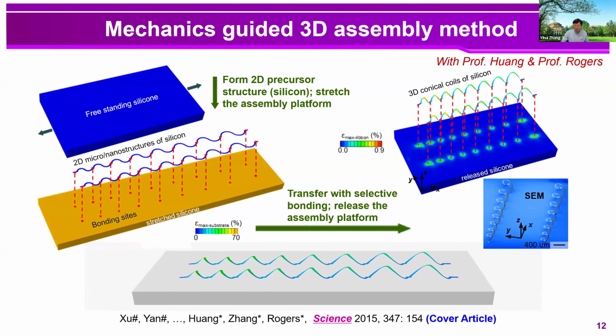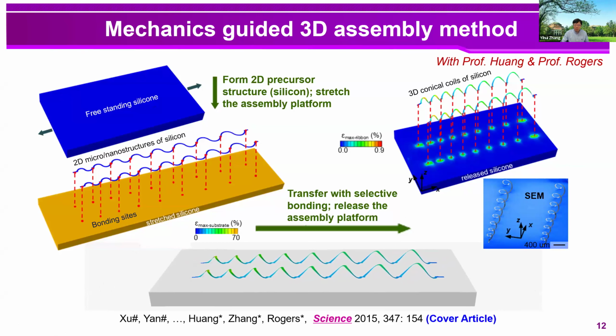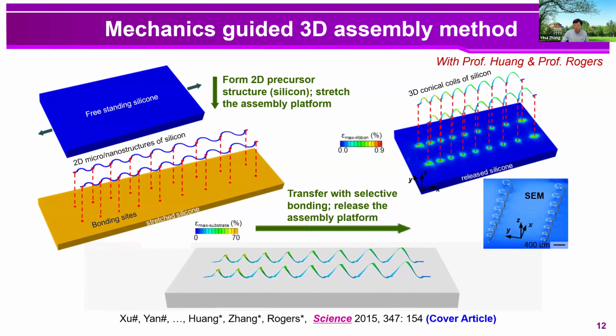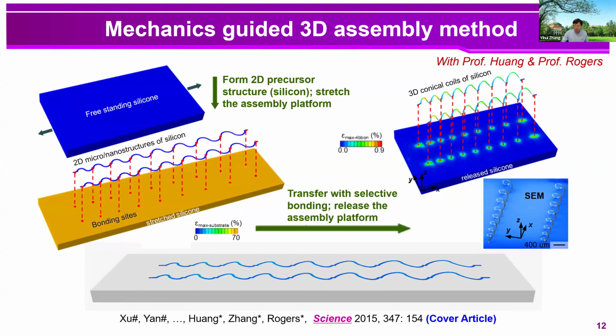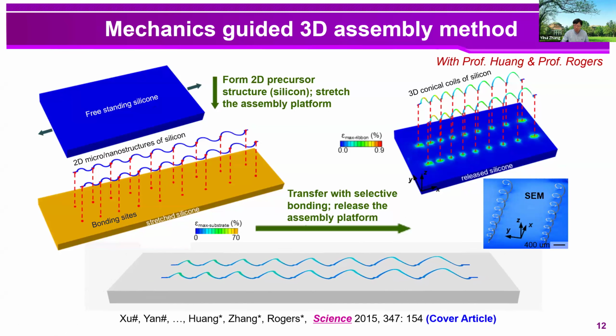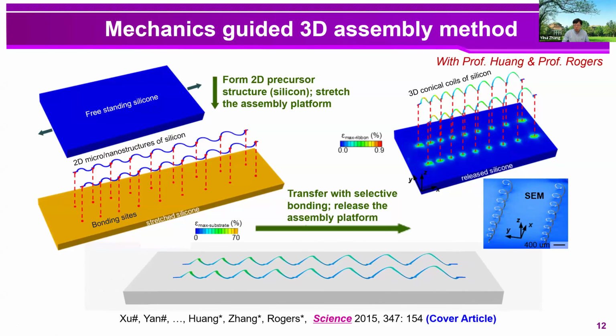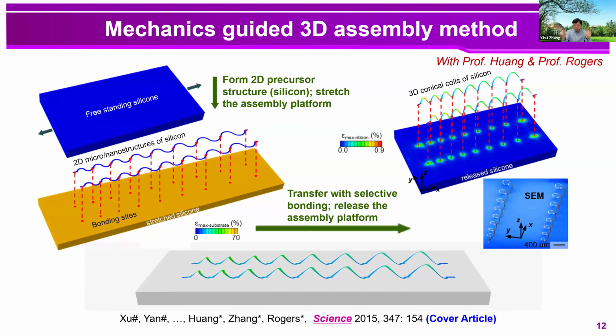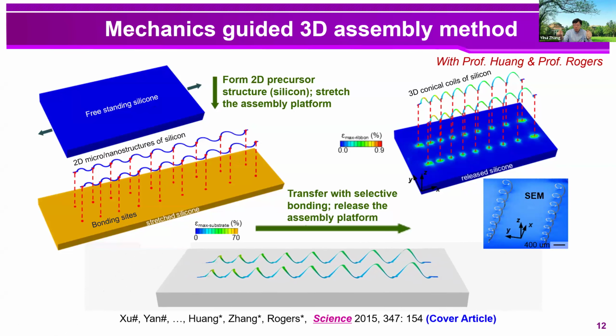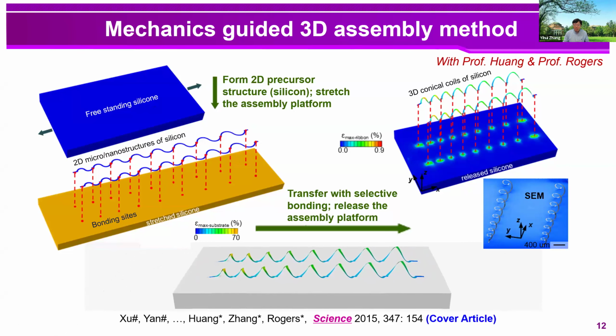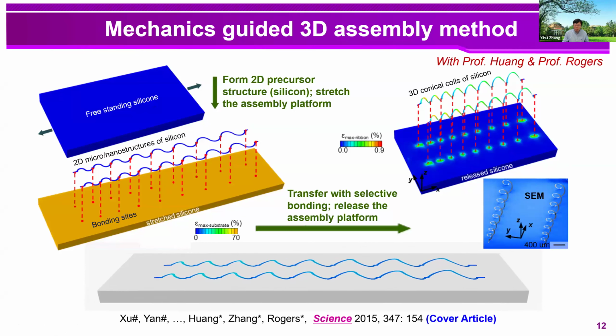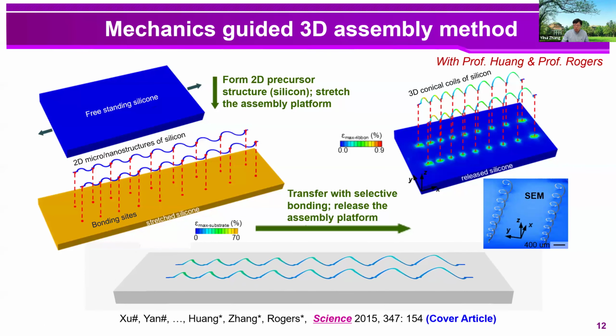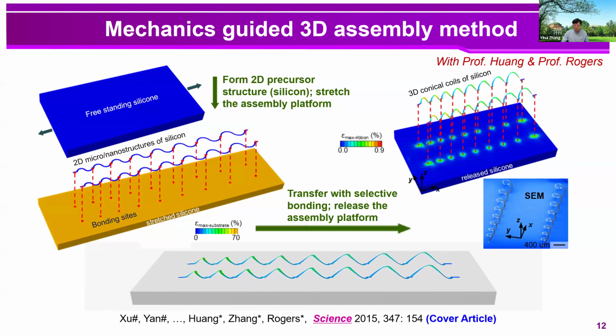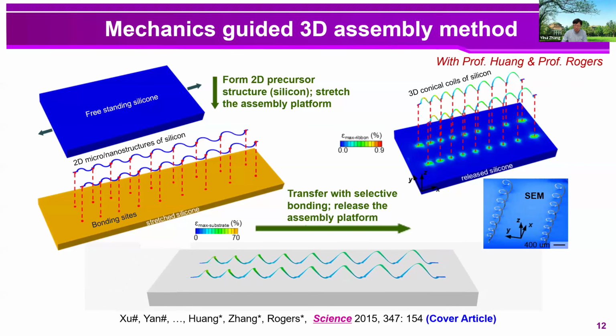Here I would like to emphasize that single crystal silicon is a very brittle material and can undergo just 2% strain before its fracture. This means that if you stretch a sample from length 1 to length 1.02, it will break. So here the mechanics play a very important role in the design because we need to ensure the safety of the structure under such a large level of compression and deformation.